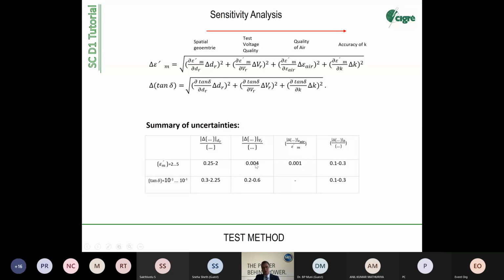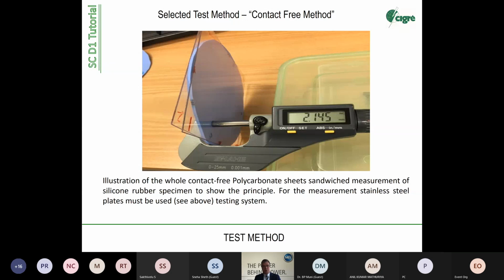The influence of voltage is not so big, and here the air gap is also not significant. So all factors that influence the spatial geometry we have to take care of. It means measurement of dimensions, measurement of thickness, measurement of the air gap, control of plane parallelism, and quality of samples, of course. Here, it's one sample. It's an easy one. It's a silicone rubber sample that was used here for illustration, how you measure it between polycarbonate sheets. The sandwich is measured, and you can see from the accuracy of the device how good you can measure.